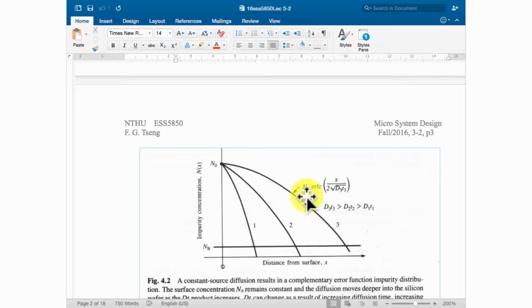So the total impurity you introduce into the substrate will be the area under this curve. As time progresses, you get more and more atoms diffused into the substrate. But the distribution will be different. You have a high concentration on the surface. The concentration is fixed at N0 because you fix the outside environment. And you have a lower concentration at a deeper area inside your silicon substrate. So this is the first type.